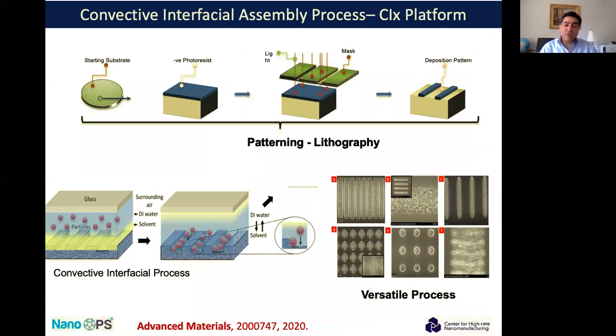Okay, so now we go to another technique, where let's say you have no way of applying an electric field in your process. And you want to also make interconnect or other types of structure. How do you do that? Well, you have your structure. Your structure can be made using trenches, using photoresist or using trenches in another material that you printed earlier, for example. And what we do here is we fill the features, the vias and so forth, trenches, using a solvent or something like IPA, for example. And then you put the solution on top of that. And then basically you get assembly in about a minute or so.